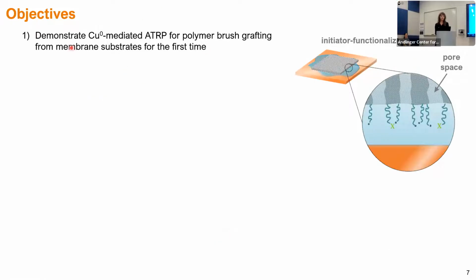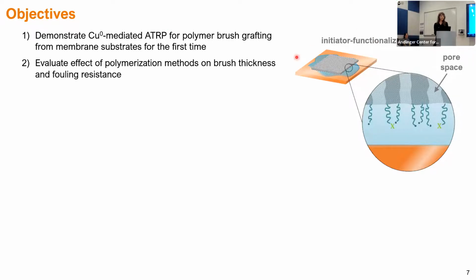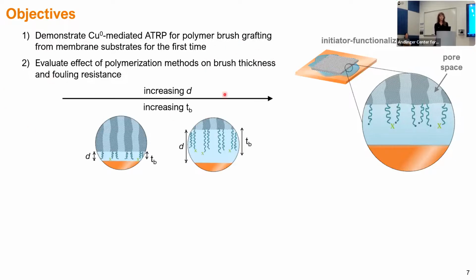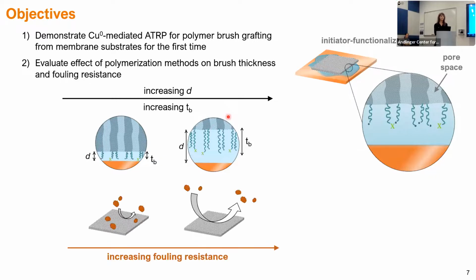So that brings me to our objectives. Our first objective is to demonstrate copper-mediated ATRP for brush grafting from membrane substrates, and specifically looking at these porous substrates, as I've illustrated here. Our second objective was to evaluate and try to understand the effect of polymerization methods and parameters on brush thickness, as well as fouling resistance. So specifically, we expect increasing that distance D between the copper plate and the substrate to result in higher brush thicknesses. And based on studies of conventional brush membranes, we expect that to result in better fouling resistance.